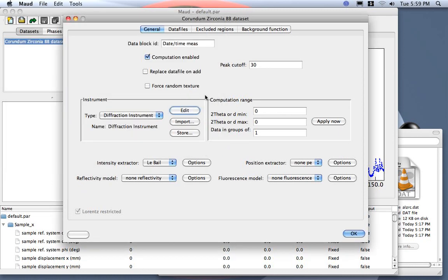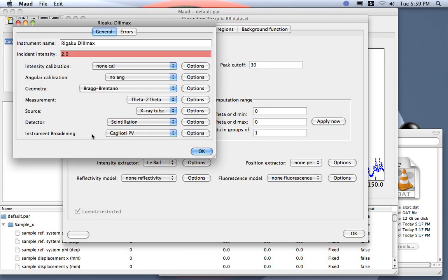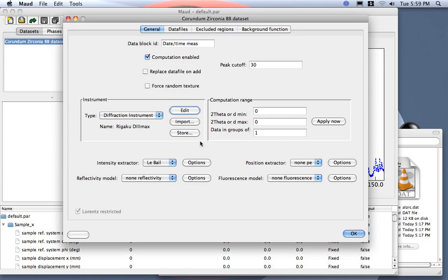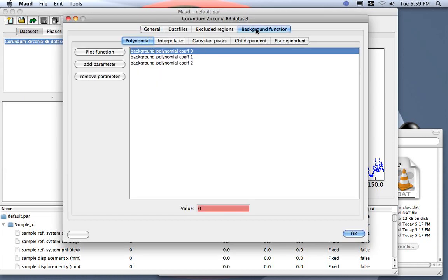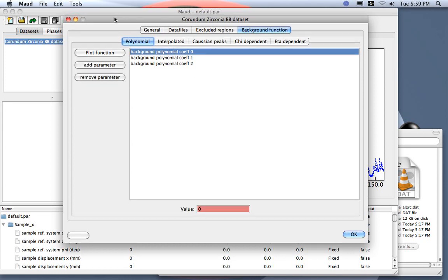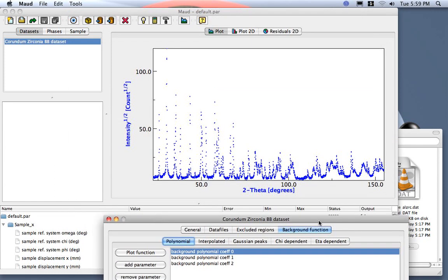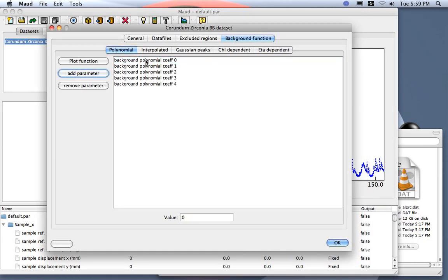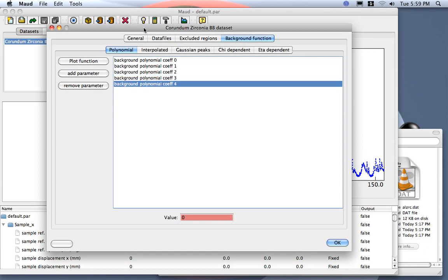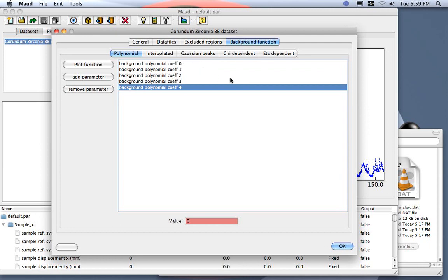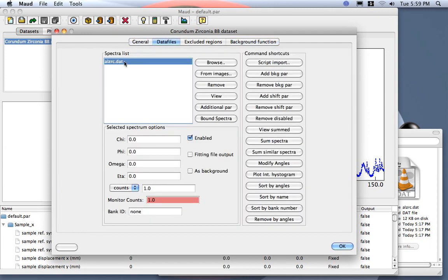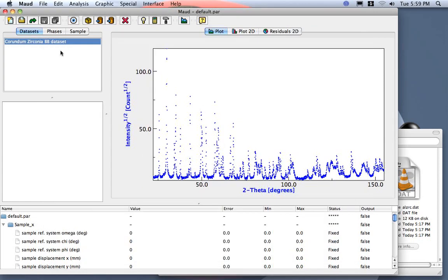In reality, okay, we don't need to modify anything, because here, in the instrument broadening, this was already set for this instrument. Okay, there will be another lesson showing how to calibrate this instrument to measure the instrument broadening defined in MAUD. Okay, now we only want to change maybe the background. So by default, here we have 3 coefficients, and maybe because we have a large pattern here, you see more than 120, maybe we just choose to use a polynomial background of 5 coefficients. Okay, the rest we leave as it is. So we have a data file, and we have just modified the background. So actually,